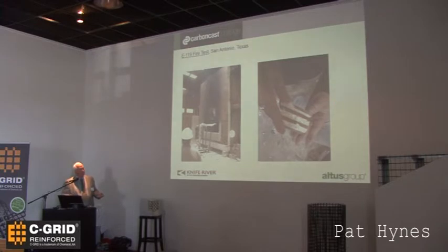What we found out was, first of all, this was a panel that was cast a long time ago in Pennsylvania. They shipped it down to Texas, and we had some dimensional problems or something, so they said, well, let's just put a fire test on it. And what we found out is the coefficient of thermal expansion of thin brick and concrete is a little different, so it popped some of this brick off. But if you look at that panel after the fire test, and it has an axial load on it right now, it's loaded. It didn't fail, it performed. And really, if this weren't a building, they'd have to go in and maybe sandblast this and clean it up. We can glue more thin brick back on to make it look like the original, and we're back in service again.